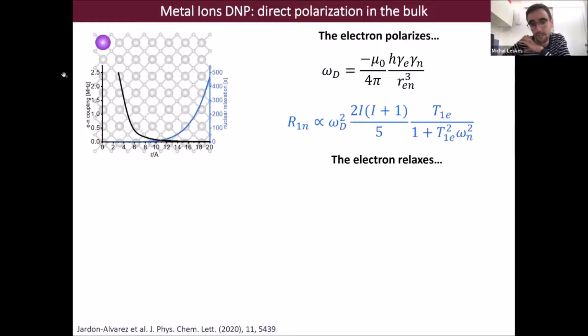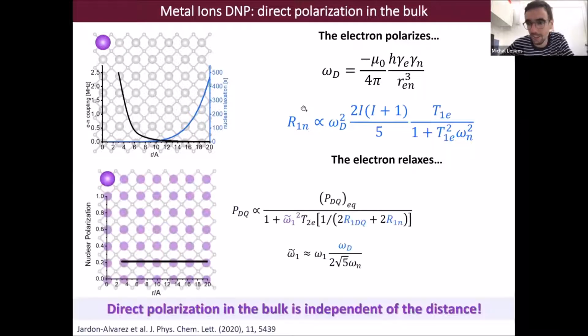So if this is the case, the longitudinal relaxation of the nuclei will also depend on the distance to the metal ion, since the relaxation time depends on the strength of the dipolar coupling. So the further away we are from the metal ion, the more time we have to hyperpolarize the nuclei before they try to get back to Boltzmann equilibrium. And it turns out that these two effects perfectly cancel each other, meaning that the DNP enhancement is actually completely independent of the strength of the dipolar coupling, as long as the paramagnetic relaxation enhancement is the main source of